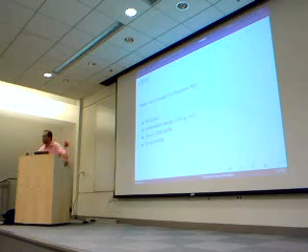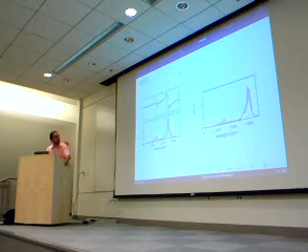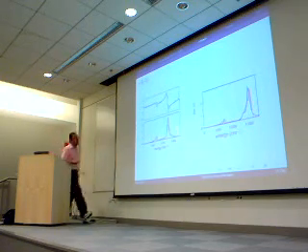To calculate a model like this, we start from a crystalline structure. And you will see it's possible to heat up the structure and simulate the liquid of this material, and then we simulate on a very fast time scale the formation of a glassy material. So we quench it. The spectrum that I wanted to show is this.